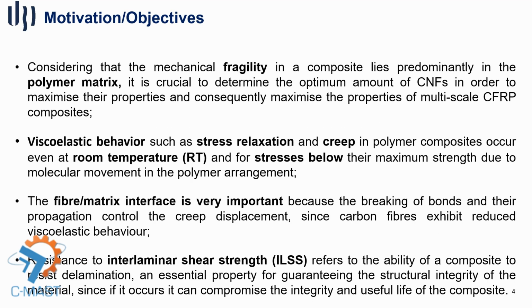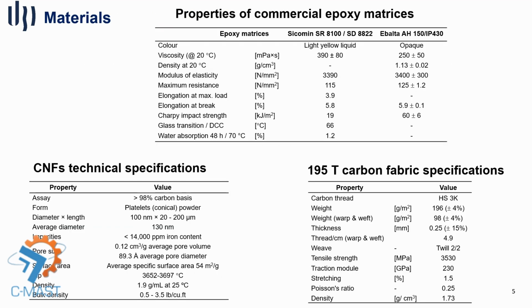But it also has its weaknesses, such as fragility of the polymer matrix, viscoelastic behavior, such as stress relaxation and creep in polymer composites, which occur even at room temperature, and the fiber-matrix interface and the resin's interlaminar shear strength. The main aim of this work is to improve the static properties of carbon fiber reinforced polymers by adding the optimum amount of carbon nanofibers. Here we can see some of the properties of the epoxy matrix, carbon nanofibers and bidirectional carbon fiber fabric applied in this work.